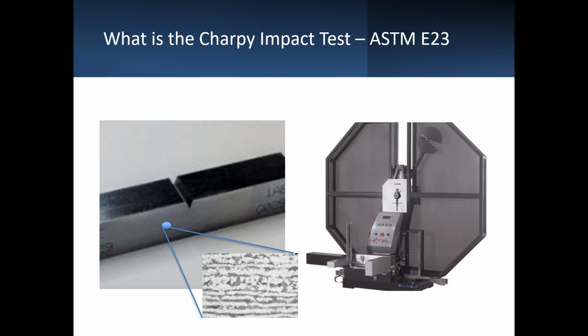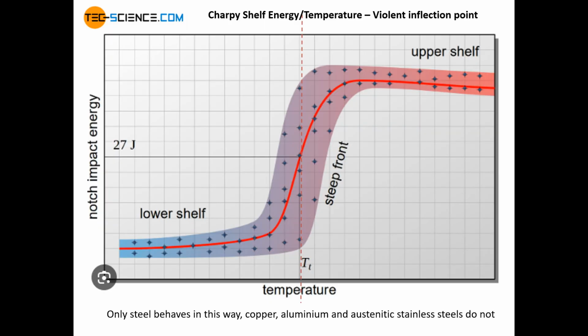Basically this hammer at the top that you can see on the right-hand side is released. It moves through, it whacks the sample that is notched, and it measures the amount of joules required to break the sample in half. And that is essentially what the Charpy impact test is all about. This test is conducted against ASTM E23.